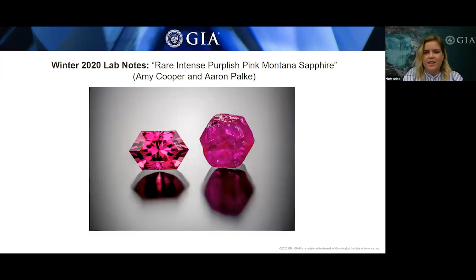Here we see a 3.93 carat, intensely colored purplish pink hexagonal modified cut sapphire submitted to the Carlsbad Laboratory for identification origin service, photographed next to a rough research stone. This stone had a refractive index of 1.761 to 1.769 and a specific gravity of 3.99, which is consistent with corundum.